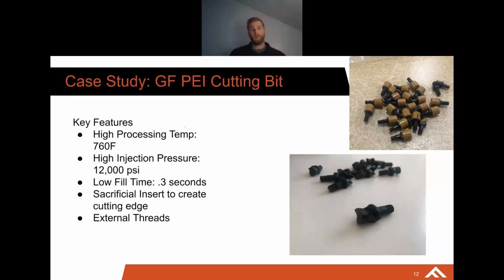Some key processing features. This is the highest temperature we've subjected our molds to, at about 760 in the barrel. The mold probably saw somewhere in that 700, 750 degrees. And the highest pressure, or second highest pressure actually, that we've shown our molds, the highest being 15,000 psi with a different ULTEM part. But this was really the first time that we had ever tried something more high requirement than polycarbonate, and it went perfectly.